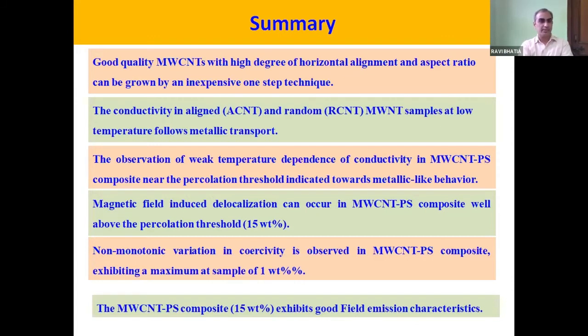Second, once you have seen the sample is good, the conductivity shows metallic transport in the CNT sample. The same CNTs, once you incorporate them with the polymer to make a percolation threshold sample, at the percolation threshold also you will get a weak temperature dependence if the aspect ratio of CNTs is high, if the distribution is homogeneous, and the material processing is done in a better manner. So this work, the second and third points, is very interesting in the composite industry because one can achieve finite conductivity at room temperature, but to have a sustained nanoscale network of CNTs within the composite is a challenge, and we can achieve it only by using a simple ultrasonication technique.